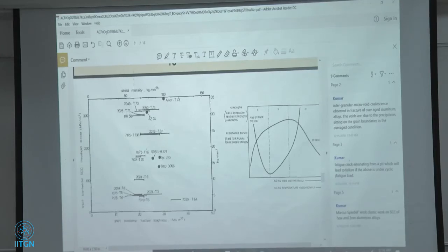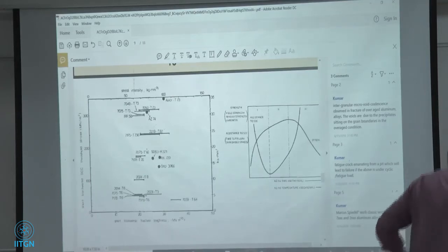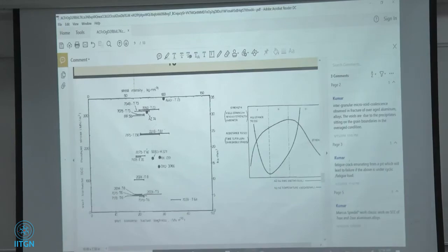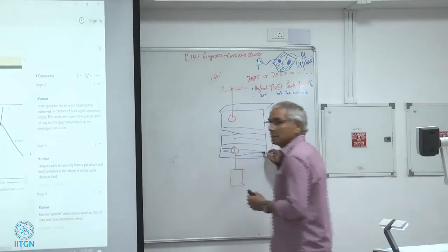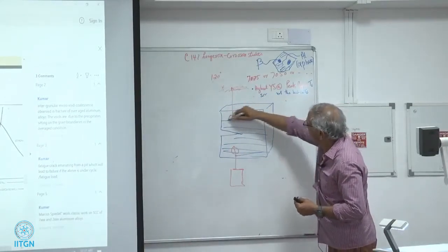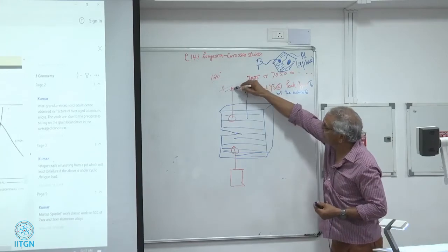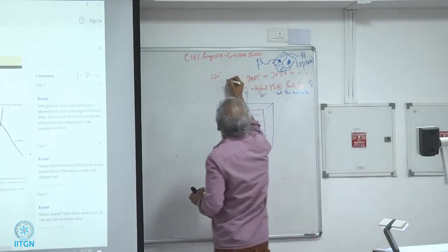The weak link in this material is in aluminum alloys. A lot of times when it's a thick plate, if it's a sheet, there is no problem. But if it's a plate of aluminum, you have to make sure that you understand this very well. So this is through the thickness. So the grain boundaries are like this, basically. You're loading it like this along the short transverse.